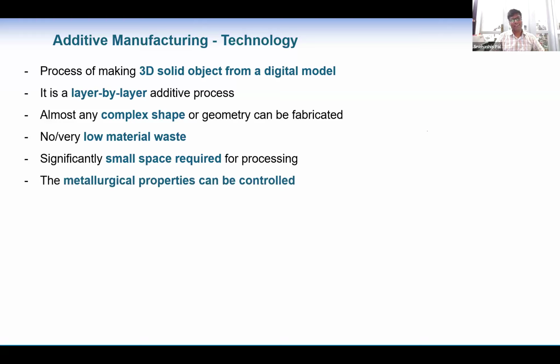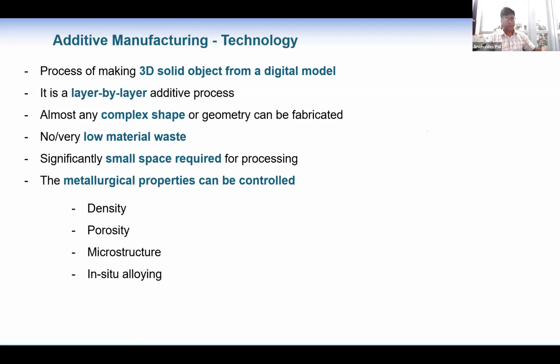In general, we can control the material properties a lot, like density, porosity, and microstructure. We can tailor these a lot. Also, in situ alloying is possible, where two material powders are put together. Let's say we need to alloy titanium and tantalum: we can get tantalum powder and titanium powder, put them together after mixing, and fabricate them together, like in situ alloying as well as fabricating the part.